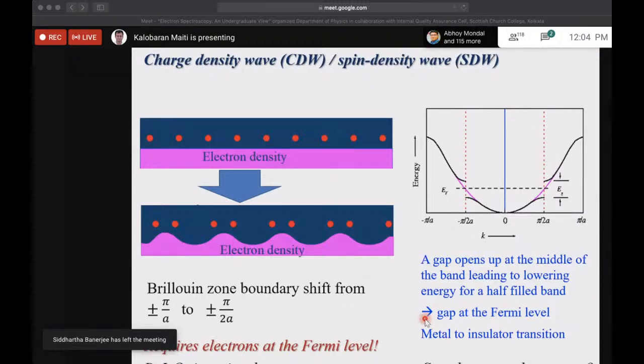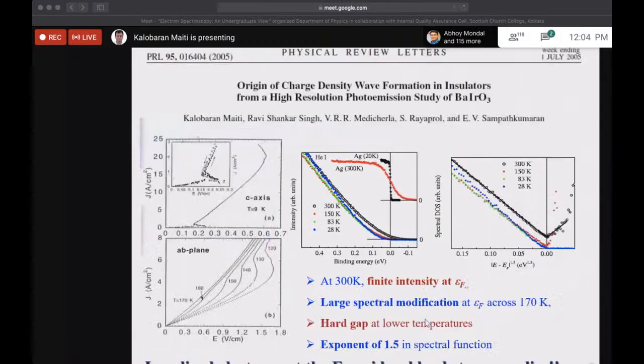Now, if you do high resolution spectroscopy, I have looked at the spectra close to the Fermi level, the highest occupied level. You can see that, although it's an insulator, you have some small density of states. This you could determine only if your resolution is very, very high, of the order of say 1 millivolt.